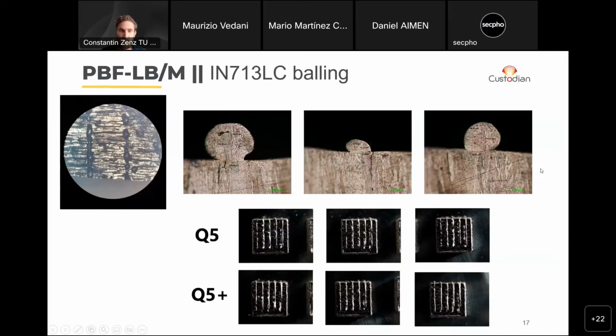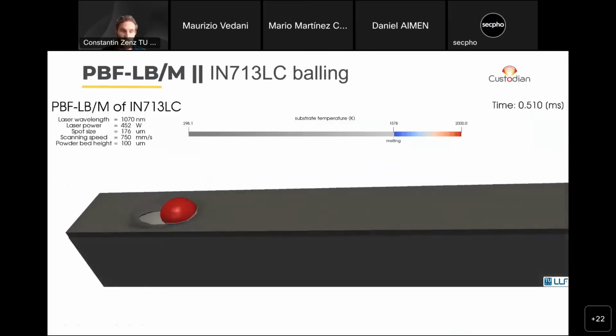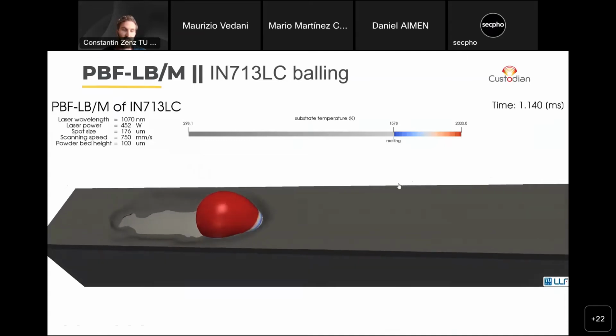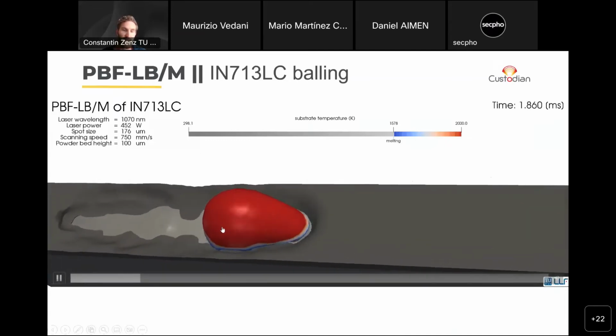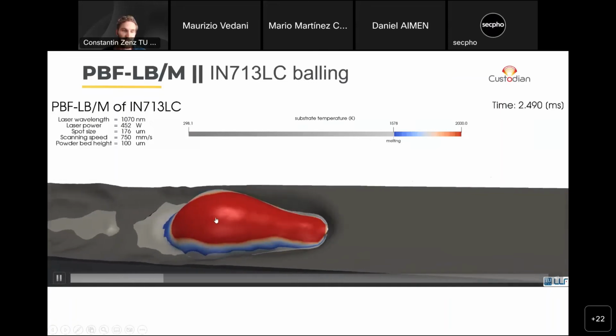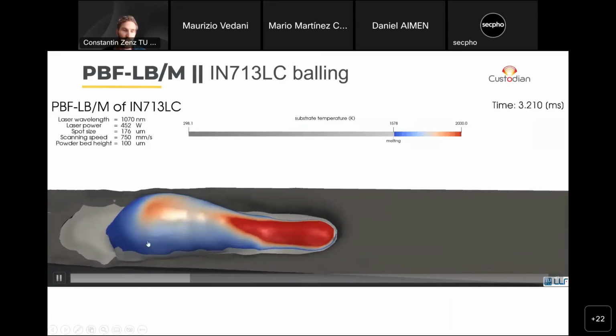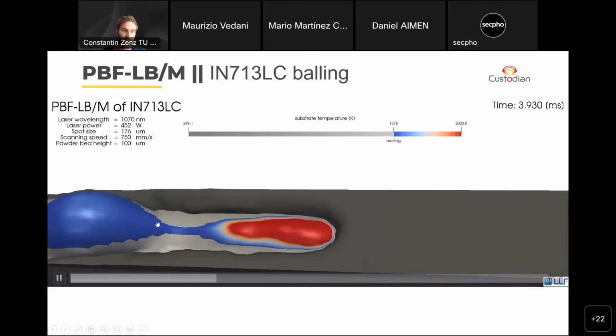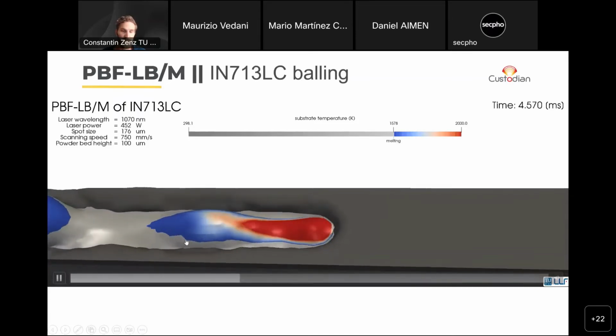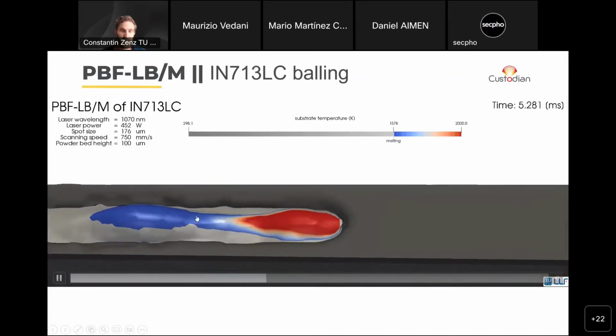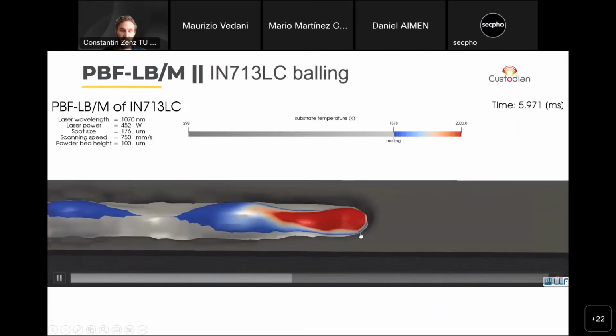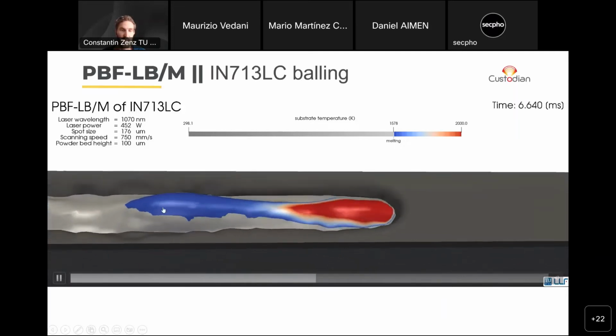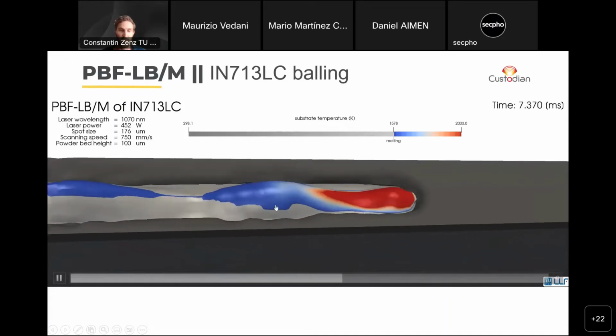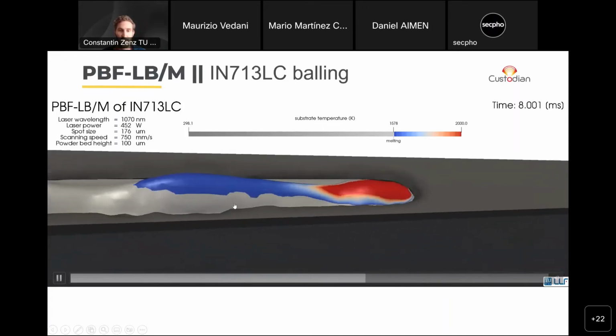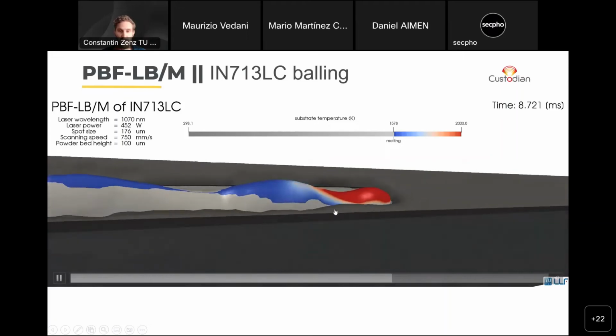And we then simulated these exact conditions, and you can see here now a video from such a simulation, and you can see how the power is not high enough to really penetrate the substrate, and then the surface tension will sort of form these sphere-like structures. And then the further this goes on, the heat input is over time, of course, increased, and it gets less, but we still cannot produce a sufficiently nice weld bead here.